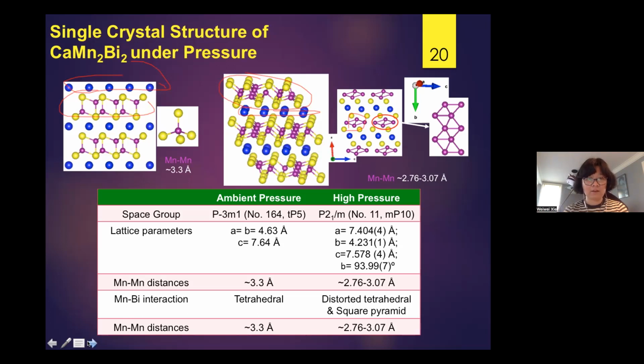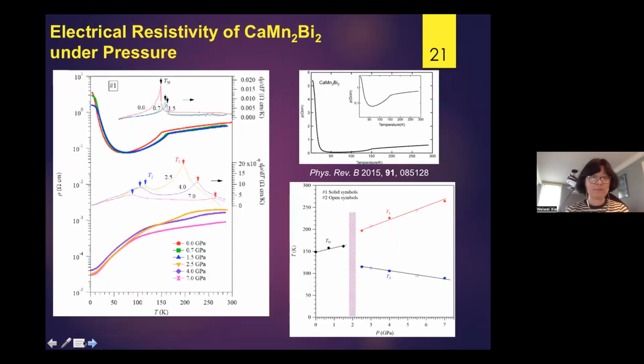After that, we did high-pressure resistivity measurements, because we tried to understand the magnetic property changes in the system, or whether there is any superconductivity. We found that below the structural phase transition under high pressure, the antiferromagnetic transition keeps increasing with pressure, which is reasonable because we make the electrons get closer to each other. After the phase transition, besides the antiferromagnetic transition, we see another transition. This transition decreases as pressure goes higher, so this is a little bit different.